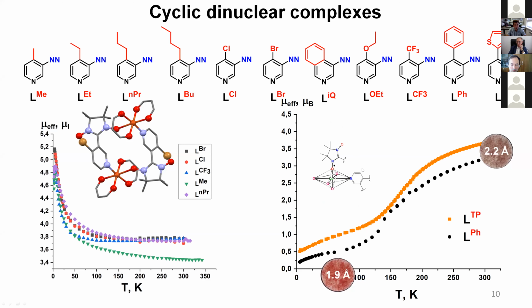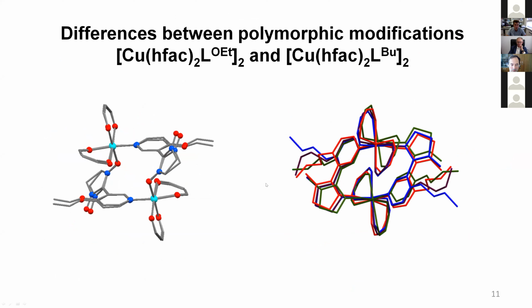Because of this, the nature of interaction between paramagnetic centers changes from weak ferromagnetic to strong anti-ferromagnetic. And we see here a thermochromic effect too, like in polymeric chain complexes. For the complexes with ligands having ethoxy and butyl substituents, these groups are so mobile that complexes with ethoxy substituents exist in the form of 2 polymorphic modifications, and in the case of the butyl substituent, we have 4 polymorphic modifications,